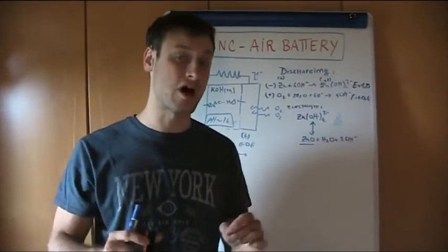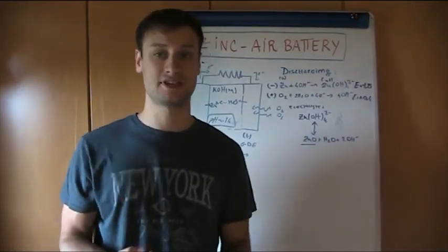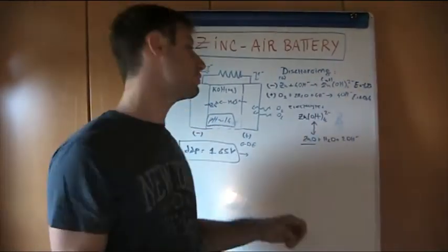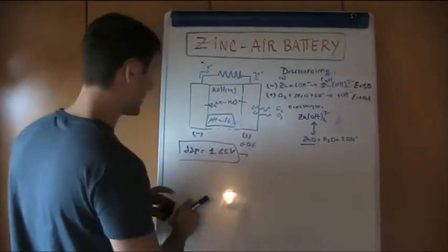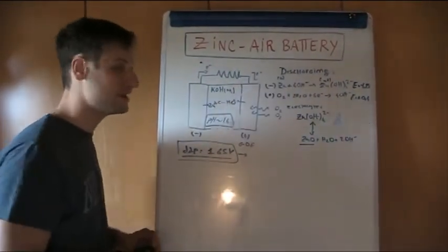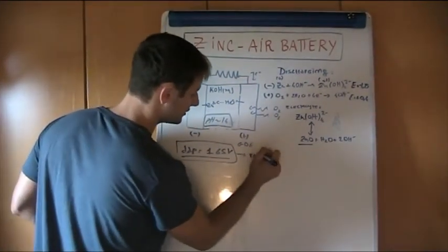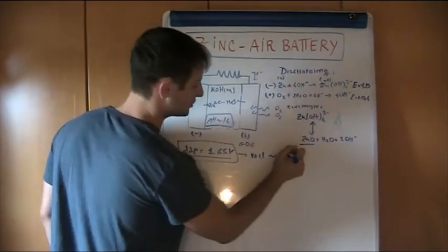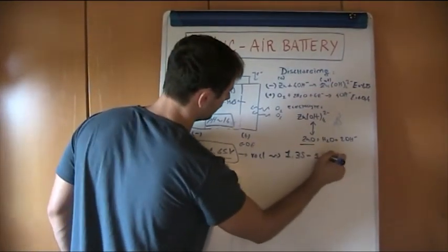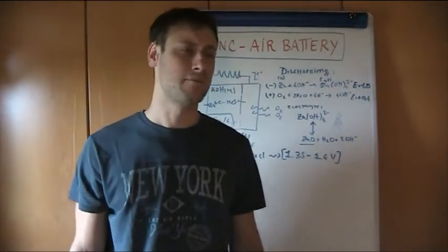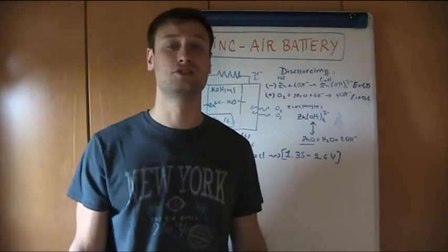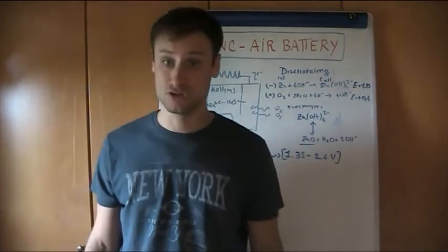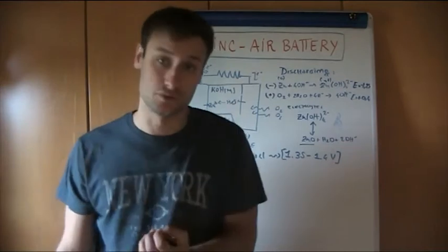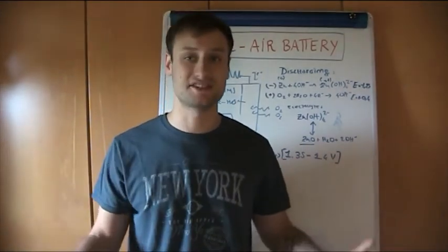We have well described these topics speaking about both thermodynamics and kinetics in electrochemistry. And so what it means is that we are not able to take advantage of this overall DDP, but the actual real DDP will be smaller, between 1.35 and 1.6. But it's a quite interesting voltage, significantly higher with respect, for instance, to a fuel cell, but also significantly smaller with respect to a lithium-ion battery. But what is interesting about a metal-air battery such as the zinc one with respect to the lithium one is the price, since the cost is reduced, and also the energy density.